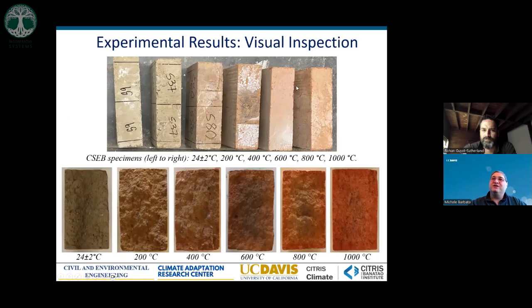These are the blocks and the visual inspection of the blocks after the heating. You can see the color changes from light brown to a reddish color. After the flexure test, if you look at the inside, you see this propagation of the red from the outside toward the inside until you reach the complete red of the 1000 Celsius. And this was the first indication of what we were kind of expecting. These blocks are transforming at the different temperatures from earth blocks to normal fired clay bricks.